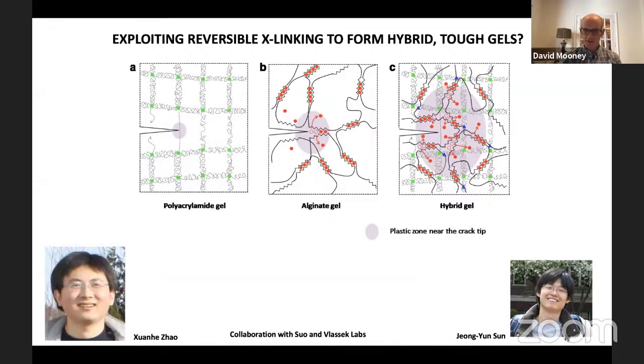And so what he and Sun, a visiting PhD student in the labs of two of my collaborators at Harvard, Suo and the Vlassak labs, were able to demonstrate together, or propose initially, was that having a combination of dissipative, stress-relaxing bonds within a material combined with covalent bonds could lead to significant toughening. The basic idea is if one has a typical covalently cross-linked hydrogel like a polyacrylamide gel, as one starts to stress it, one puts a significant stress on individual bonds, the stress becomes so great that those bonds fail, and then you get stress propagation throughout the material.